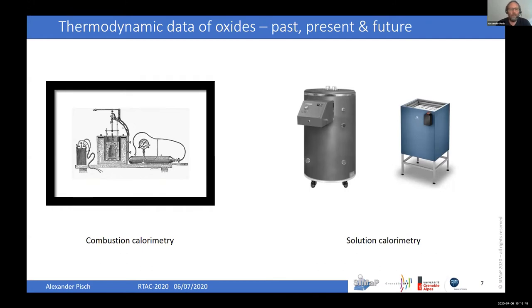In the case of lime or magnesia, it may be straightforward because CaO or MgO is formed. But in the case of systems where you can have a series of multiple oxides, I think of titanium or other high valence oxides, you may not end up with a single oxide. So it's very important to characterize carefully your sample after reaction. And sometimes it's not even crystalline, but you get an amorphous product. So it's not always straightforward to get high quality data out of combustion calorimetry.